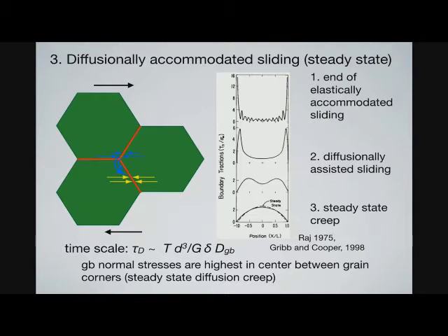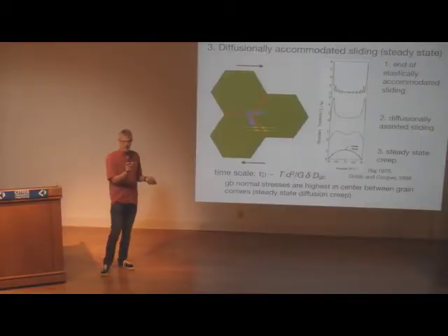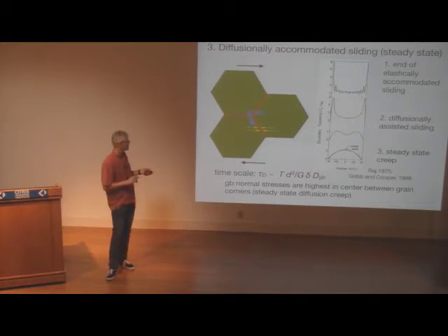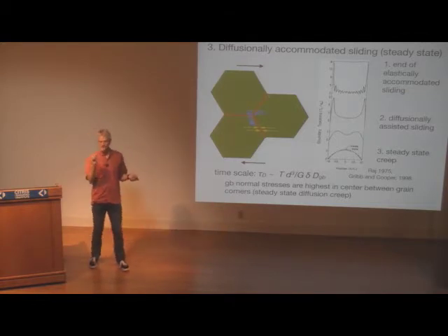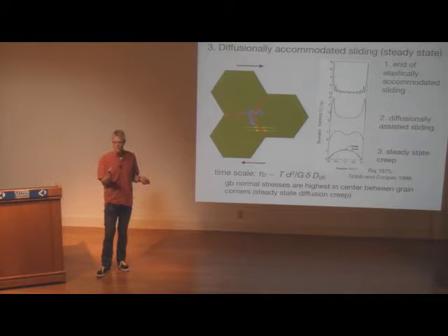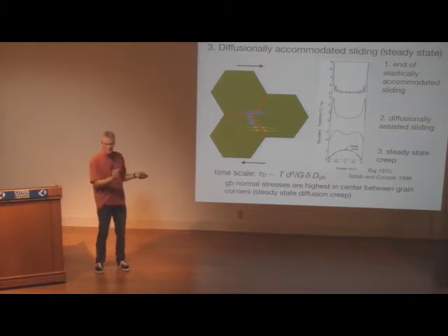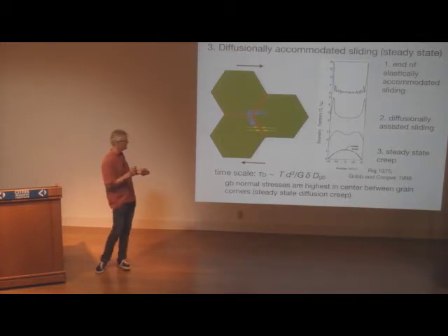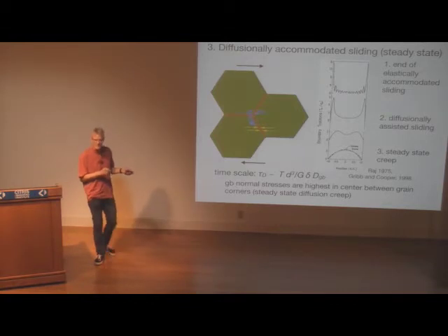The big difference to diffusion creep is that you still have these elastic restoring forces at the grain corners, so that's the anelastic part. For the viscous deformation, you permanently change the grain arrangement. Seismically, because you're just at very small stresses, very small strains, you just slide the grain boundaries past each other by a little bit without changing any of the geometry. You're just starting the process of diffusion, but you never complete it. You never complete diffusion entirely.